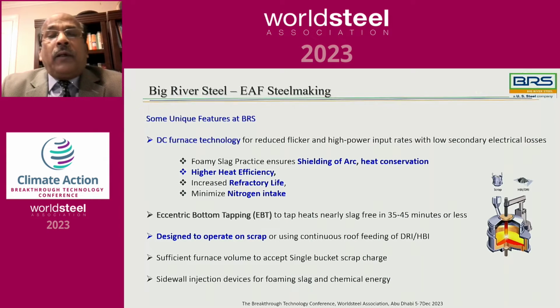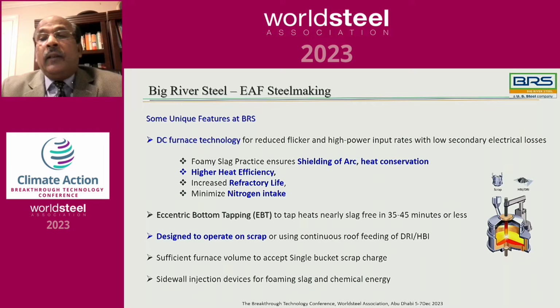So just a few things about the arc furnace steel making at BRS, some features to save energy and also make quality steel production. BRS uses a DC furnace technology that reduces flicker and high power input rates. And we also practice foamy slag practice. With the introduction of foamy slag, the arc is shielded, therefore we conserve the heat, and it also saves the refractory life or minimizes the erosion of the refractory because the heat is shielded or insulated by the slag. And also, since the arc is shielded by the slag, the nitrogen intake in the steel is also low.